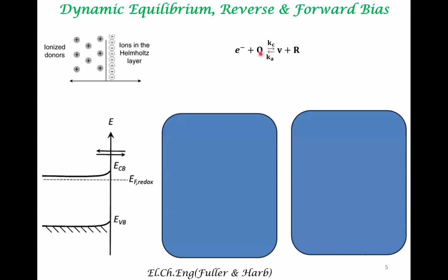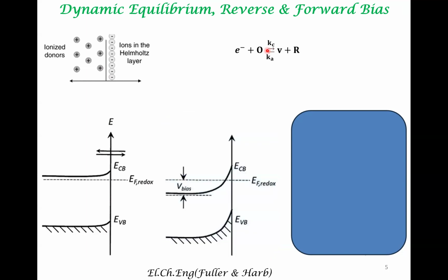So one way to accelerate the anodic and cathodic process is by applying bias. So that's the way we polarize an electrode and increase the rate of one of the rate processes, right? So this we have already done in the context of, let's say, a metal electrolyte interface. Here we have a semiconductor electrolyte interface. The quintessential feature of a semiconductor electrolyte interface is the band bending, right? This is the distinct characteristic of a semiconductor electrolyte interface. There is band bending, right?